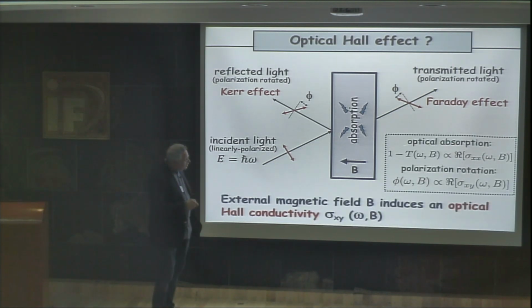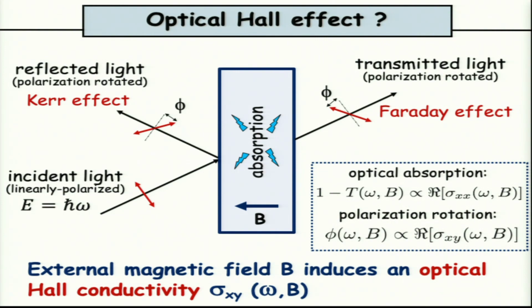So you can clearly have access to the transmission of the light through the sample just by having access to the optical conductivity in the system. This optical conductivity depends on the energy of the light and also on the magnetic field, and you take the real part of it in order to get the transmission. On the other hand, the polarization rotation is directly proportional to the real part of the optical Hall conductivity, sigma xy, which is also dependent on the energy of the incident light and on the magnetic field.